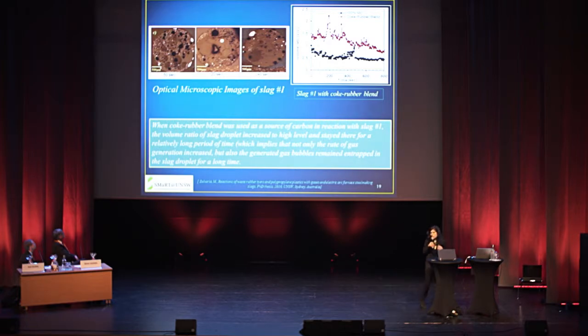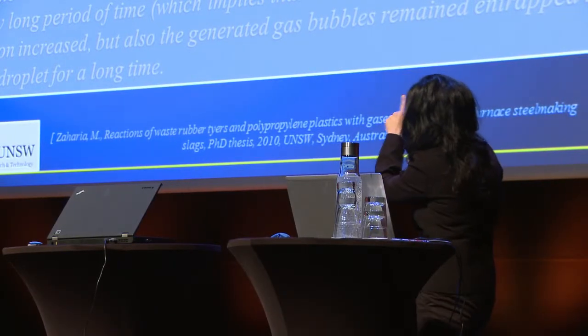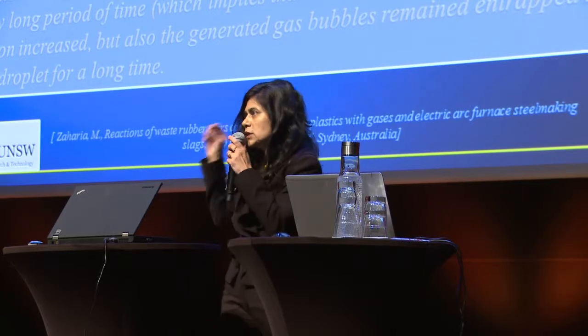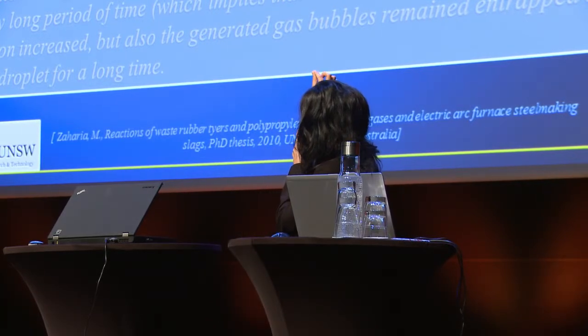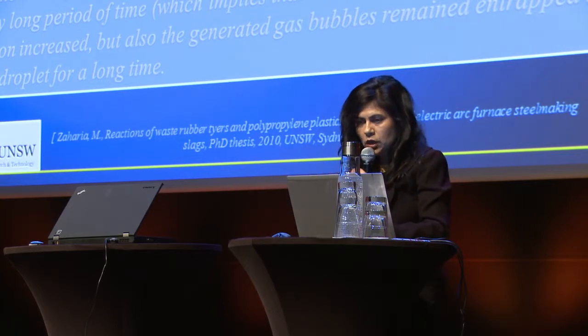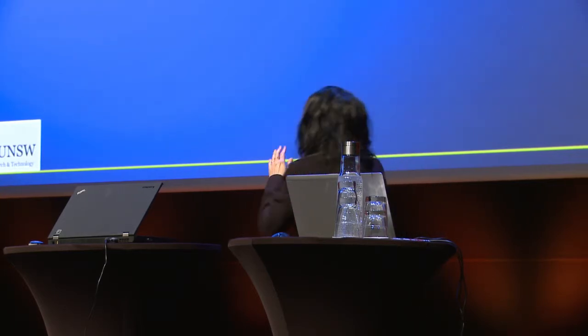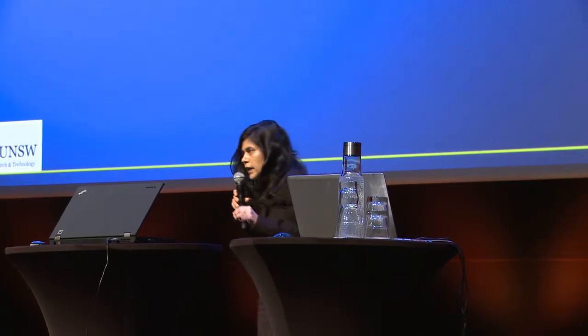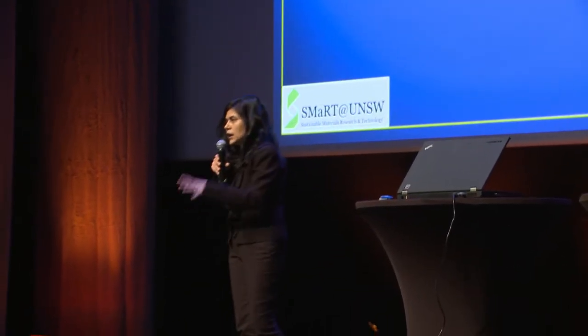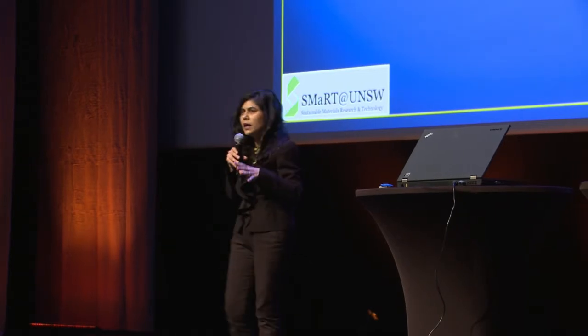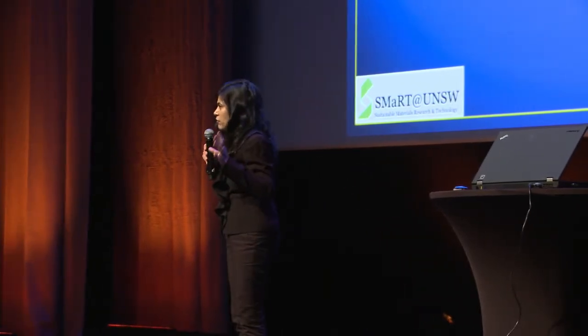As I said, a lot of the scientific work actually shows you the microstructure of the slag at high temperatures, and you can see those bubbles over a period of time, which are basically those dark gas bubbles inside being trapped over a period of time, showing good performance. So look, we've talked about why we need innovation in this space. What exactly are we trying to achieve with green manufacturing? One of the things we want to be able to do is convert waste into value. There's no point saying we're recycling something and you make a new product and that product ends up in landfill after 2 months. So that's the important message here. It's not about downcycling and just kind of doing recycling for the feel-good of it.